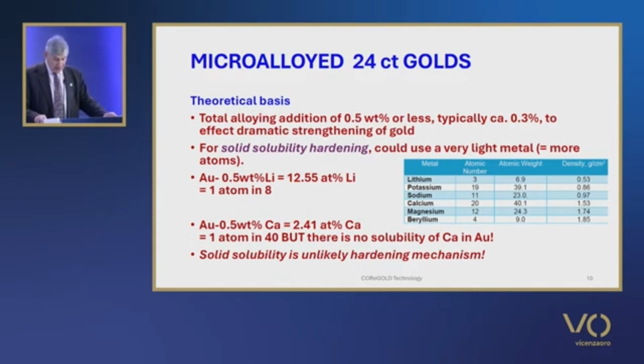Significant solid solution hardening by such small weight additions is only possible if the alloying metal is very light. That is, it has a low density and has a very small atom size compared to gold. If we examine the periodic table, the light metals that might possibly be microalloying additions are in order of density: lithium, potassium, sodium, calcium, magnesium and beryllium, as we can see in the table on the screen.